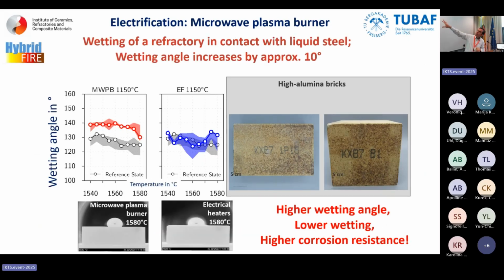As well, we have treated some bricks, alumina-rich bricks, which were in contact with a melt, an iron melt, a steel melt, and we have seen we have much lower wettability. We have a 10-plus increase of the wetting angle. Somebody would say why? Because the plasma burner has NOx, the plasma burner has O3. The plasma burner creates radicals. You always have positive issues, but there could also be bad issues. No? NOx, healthy, no? Ozone is also not nice. No? It smells like a chlorine environment.